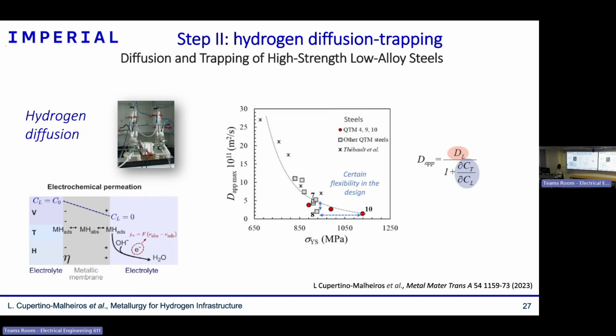For the first part of this research, I used the permeation experiment I talked about before. With this experiment I obtained the diffusion coefficient, a measurement of the speed of hydrogen moving inside of these metals. Here it is plotted as a function of the strength of those steels. You can see that the stronger those steels, the slower the diffusion kinetics. Basically, the structural features that are hardening these steels are also trapping hydrogen, with small flexibility in the design, but the correlation is quite strong.